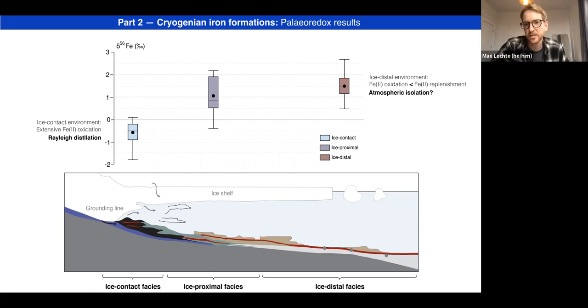So in the ice distal facies, you see only really strongly positive iron isotope values. And again, this is interpreted to represent partial iron oxidation and low oxygen values, potentially consistent with isolation from the source of oxygen from the atmosphere. Whereas the ice contact facies are either unfractionated or negative.